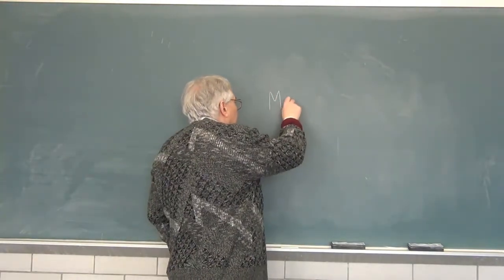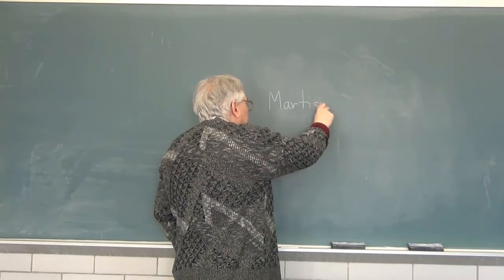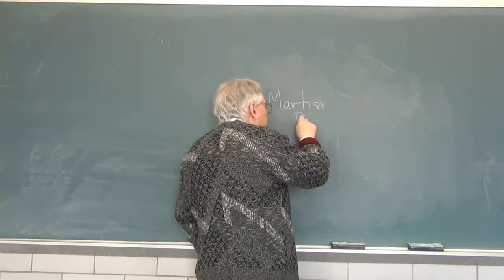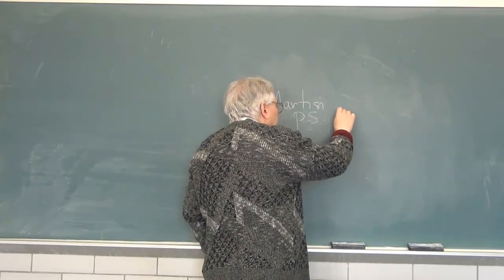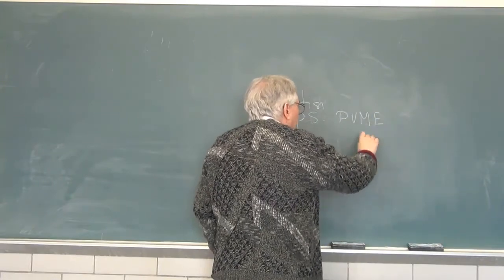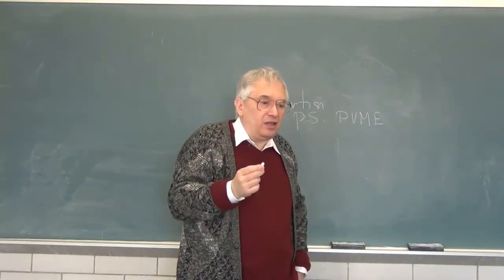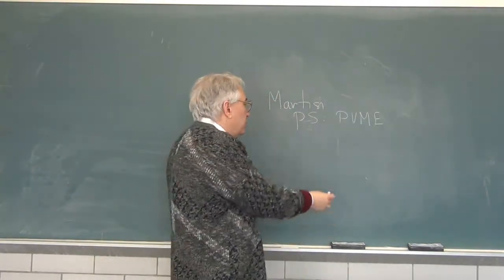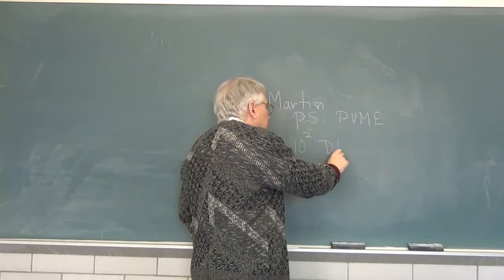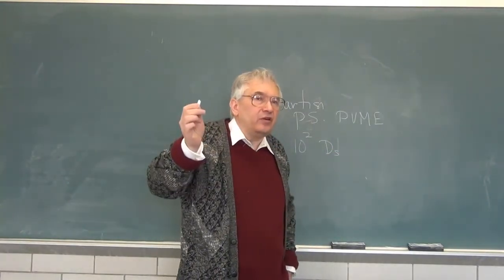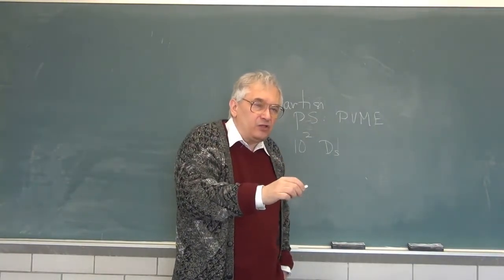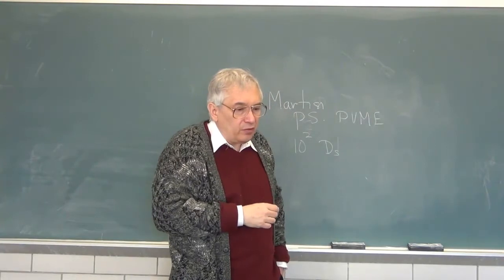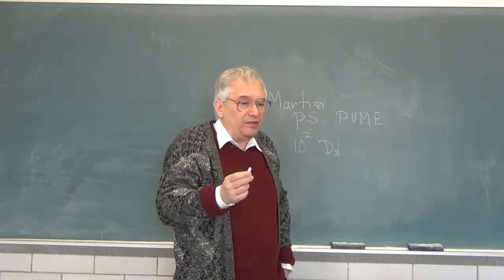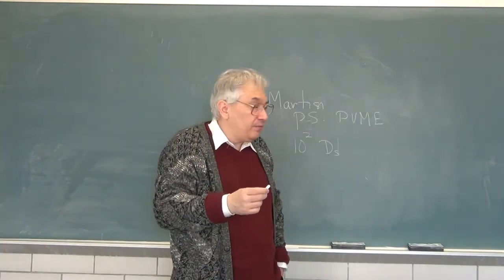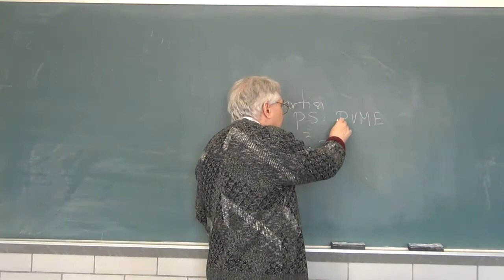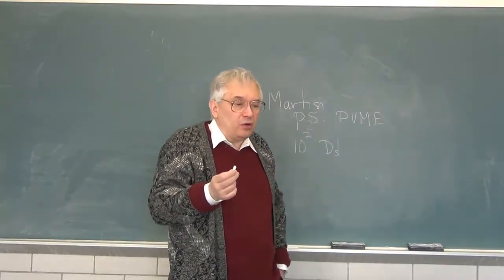which is a study due to Martin. And Martin also looked at polystyrene in PVME solutions. He actually looked first. This is among the early work on this. His measurements cover a range of about 10 to the 2 in self-diffusion coefficient. That is, the diffusion coefficient starts out at one value and it falls to about 1% of its value at the lower end of the curve. He has several different polyvinyl methyl ethers and a joint fit reflecting the various sizes of the probe gives us the curves you see, which work reasonably well.